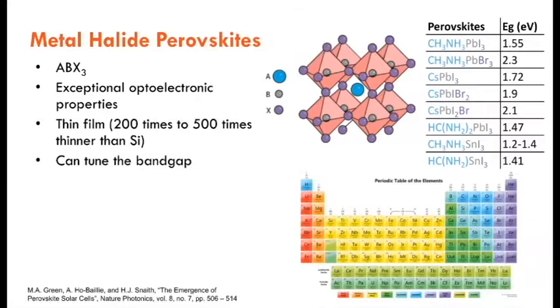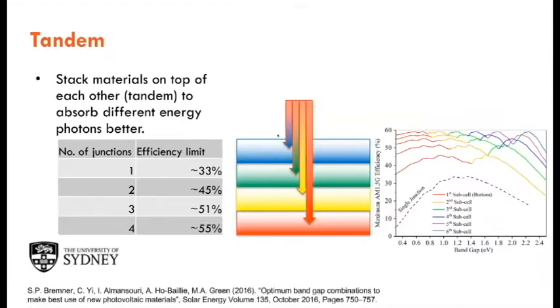Compared to conventional silicon solar cells, they are around 200 to 500 times thinner. What also makes it so good is that we can tune the composition to tune the optical properties. The blue circle here is the cation, which could be cesium, methylammonium, or formamidinium. So it could be an inorganic perovskite or an organic-inorganic hybrid, surrounded by these lead halide cages. If we can tune the composition, we tune the band gap, which means we can absorb different parts of the solar spectrum. So we can stack different types of perovskite on top of each other to form a tandem.